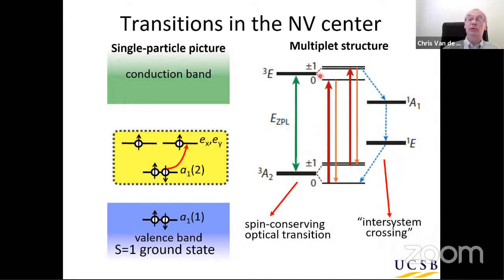Okay, but once you're in the excited state, there is actually also a non-radiative channel available where the spin flips. Okay, this is what I mentioned before, that spin orbit coupling, etc., is very important. So if you get into that non-radiative channel, then the electron goes down to the ground state, not by emitting photons, but by losing energy through lattice vibrations. This is referred to as the intersystem crossing. So I won't go into detail about this, but just show this to illustrate the importance of understanding how radiative and non-radiative transitions occur in these centers, because that allows us to calculate rates for these processes and allows us to decide how to optimally manipulate and control the center.